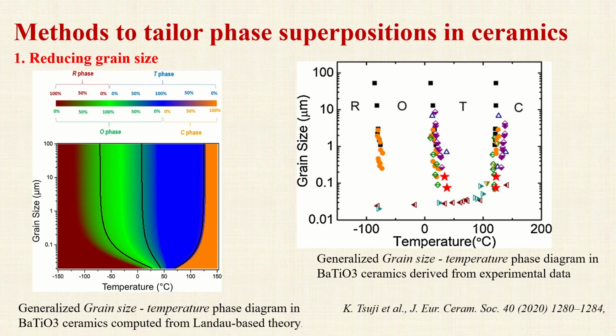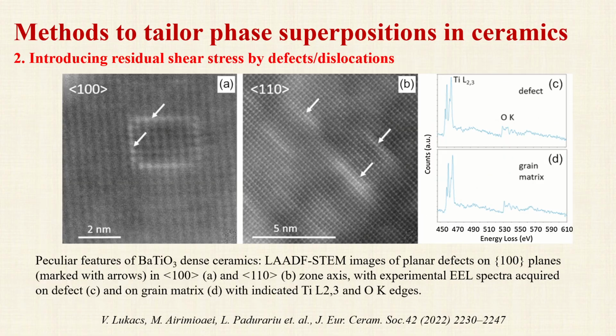In fact, this diagram was initially proposed in literature by other authors, but without the color scale and excluding the possibility of phase coexistence. In other words, assuming sharp transition of the phases. We consider that this diagram explains the discrepancies between the experimental results proposed in literature by many authors working with similar samples. The best collection of the results that were reported in literature are presented in the cited article.